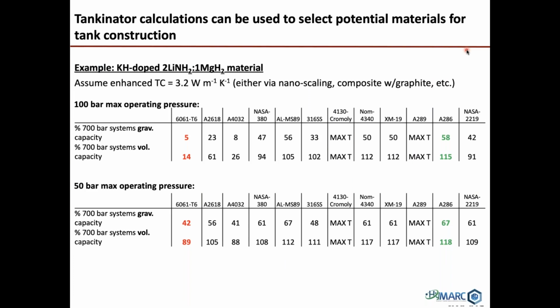We also want to look at different tank construction materials. So as I mentioned, 316 stainless is certainly standard. It's what's used to make pressurized gas cylinders for hydrogen. And what I'm showing in a couple of these tables here, I'll guide you through it. This is the gravimetric and volumetric capacity, the percent of what you would have at 700 bar. And this is assuming an operating pressure of 100 bar. So there's a whole bunch of alloys along here. Here's 316 stainless. And what you see is that it does okay on the volumetric side, but it's really lousy on the gravimetric side. And that's just because it's so heavy.